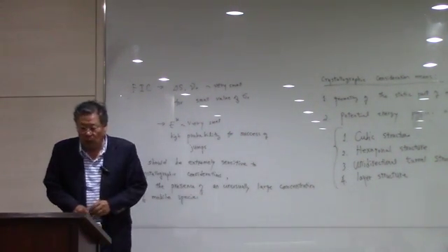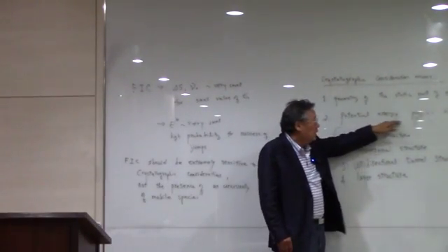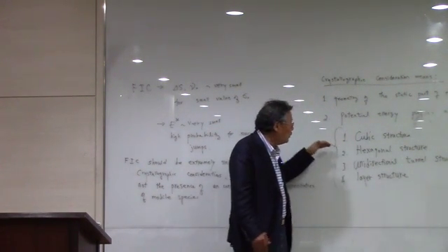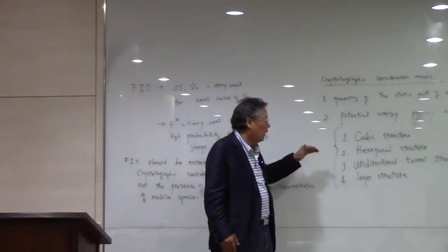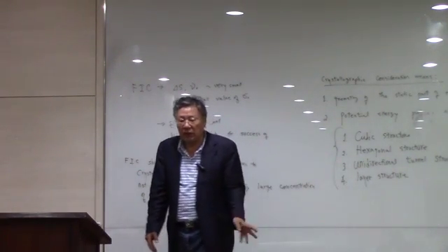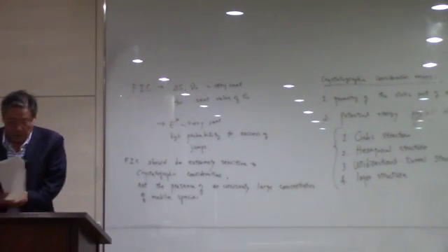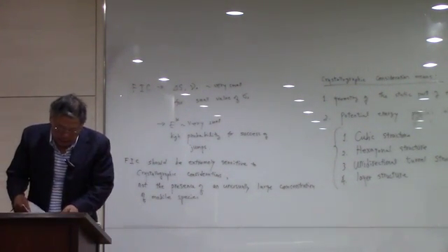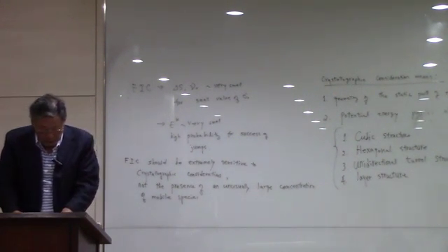If we have abnormally low potential energies in a cubic structure, or if you have abnormally open structures for the mobile species in hexagonal, and the tunnel and the layer structures, like beta alumina and potassium hexatungstates and so forth. So you guys have to look into the details of this, which is described in the last section of the handouts to understand the fast ionic conductors.